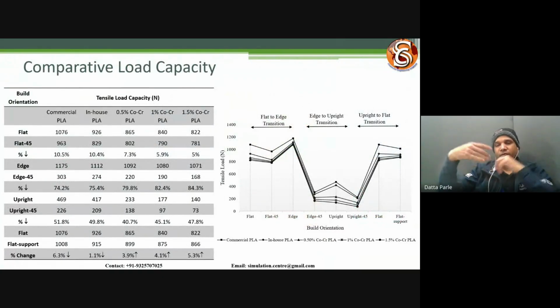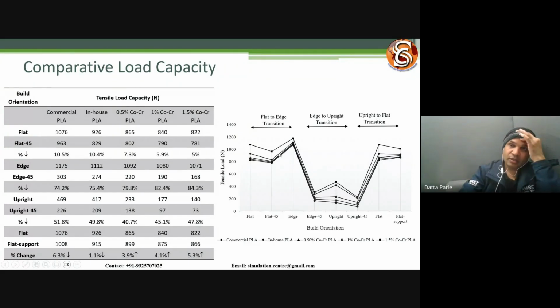Then we manufactured those different filaments, and again we compared the strength and load capacity. We found this commercial PLA is still the highest in loads. Then you have the in-house PLA, and as we add material, metallic particles, the load started decreasing. In most cases the load decreased by varying amounts. In some places we saw a bit of increase, but it's not that significant.